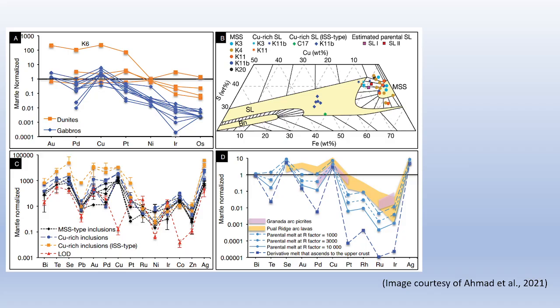Finally, panel D pulls it all together. These are modeled parental and derivative melt compositions compared against natural arc lavas from Granada and Paul Ridge. And the story is clear. The parental magmas of Chilas Complex started with decent amounts of copper, gold, and palladium, but after interacting with just a small volume of sulfide, modeled with melt to sulfide ratios of 1000 to 10,000, the derivative melt that ascends toward the upper crust loses more than 95% of its PGE, most of its gold, and a large share of its copper.